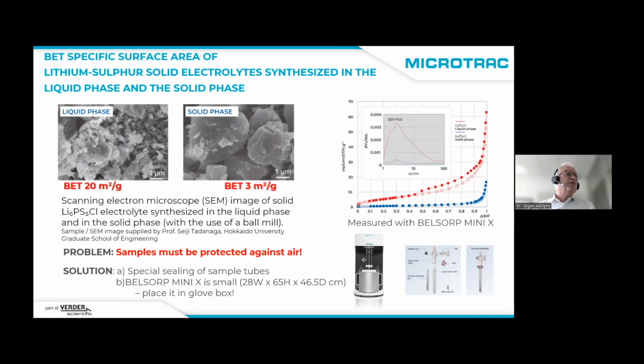And the surface areas also are quite different, what you could already maybe guess from the electron microscope pictures. So we get here a BET surface area of 3 square meters per gram for this electrolyte made from the solid phase, and around 20 square meters per gram from this one made from the liquid phase. So this is a machine where we can determine surface areas and pore sizes in the range up to about 100 nanometers.